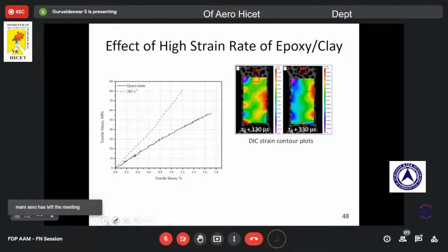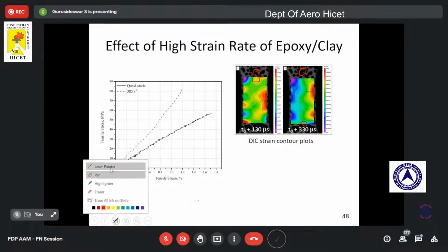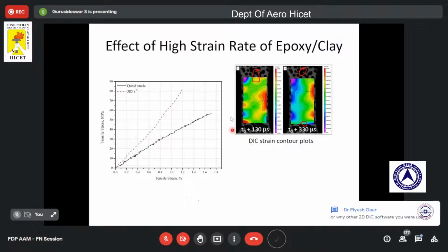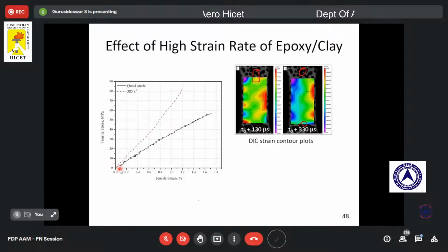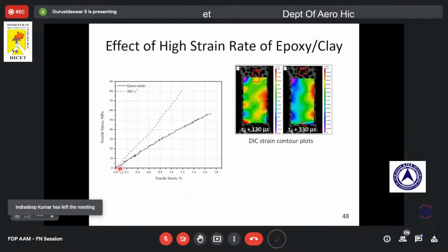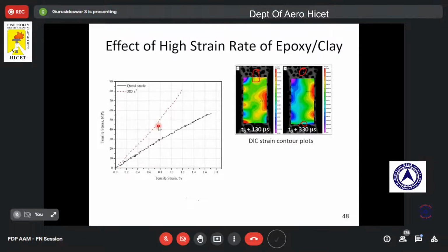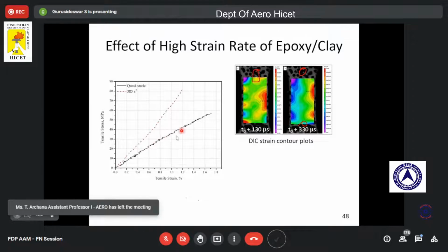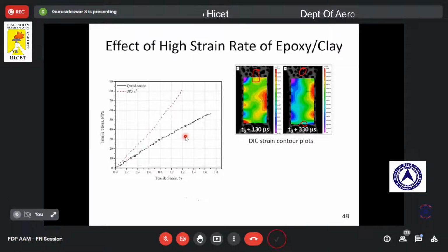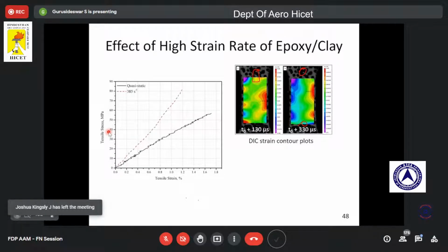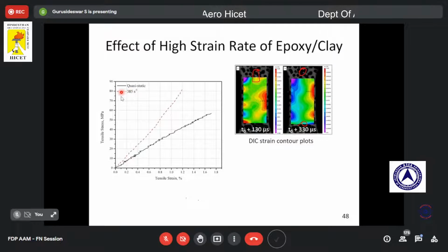But with the help of this DIC, it is possible to get the strain over the entire surface, or I can say full field strain data. So this is what we get from the DIC technique. Here I have plotted the stress strain curve of an epoxy clay sample at high strain rate. The black shows the quasi-static data, done at quasi-static loading, and the red shows the tensile stress strain curve at high strain rate.